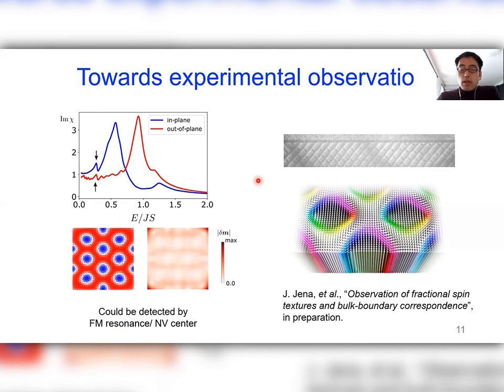But another important problem is that we need to stabilize fractional antiskyrmions to realize magnonic corner states. Recently, we were able to observe these fractional antiskyrmions in Heusler materials. Here, near the sample edges, we can see triangular-shaped objects cut in half at the sample boundaries.